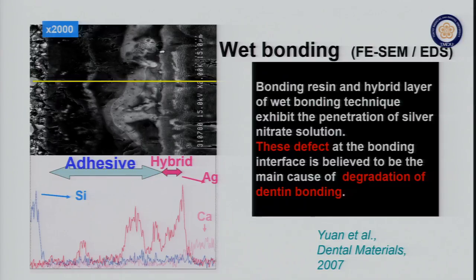Then the silver nitrate solution can penetrate into the space at the interface. After that, we try to detect the amount of the silver penetrating into this interface. The amount of silver is indicated with a red line here along this scanning line. You can see the silver peak here in the bonding resin, also in the hybrid layer. Also at the bottom of the hybrid layer, a very high peak of silver is detected. It means that there is a space at the interface. This defect at the interface is believed to be the main cause of the degradation of the dentin bonding afterward.